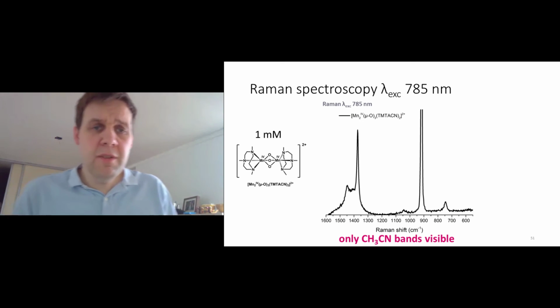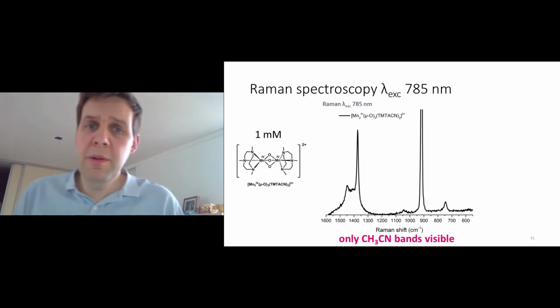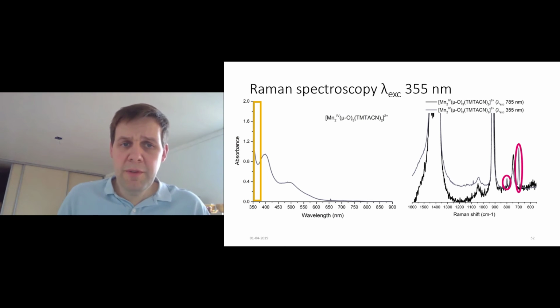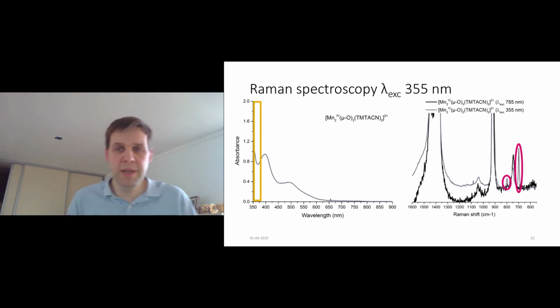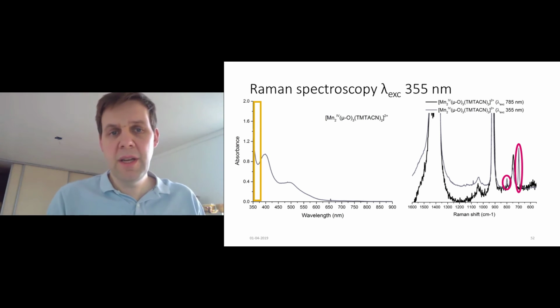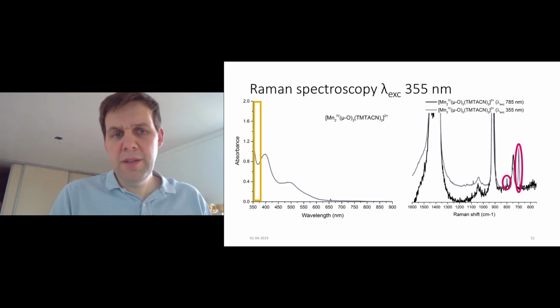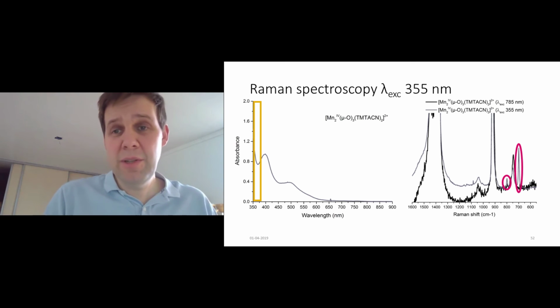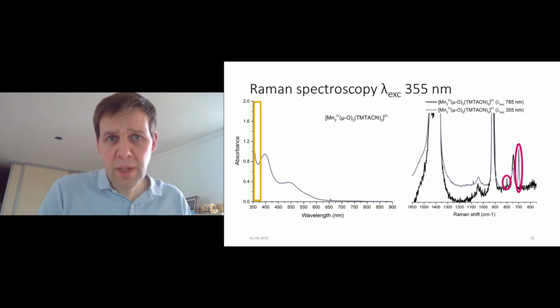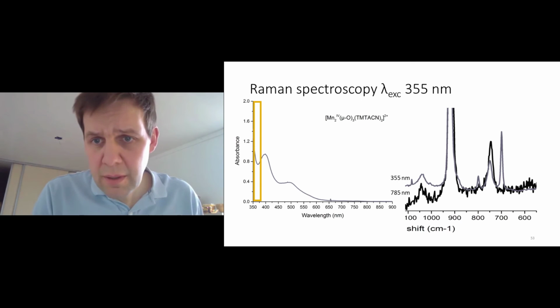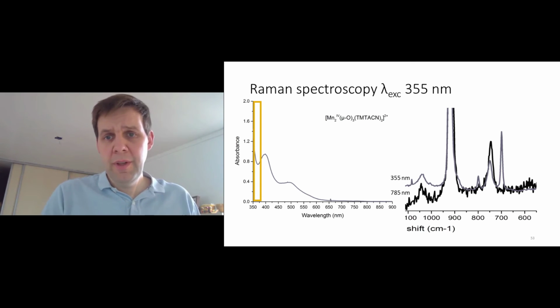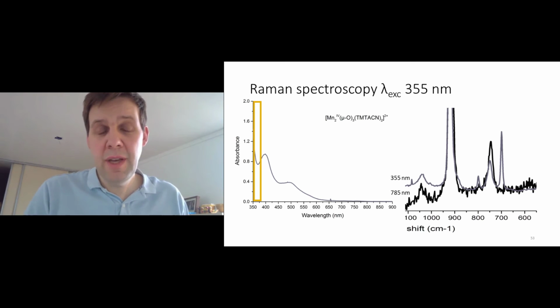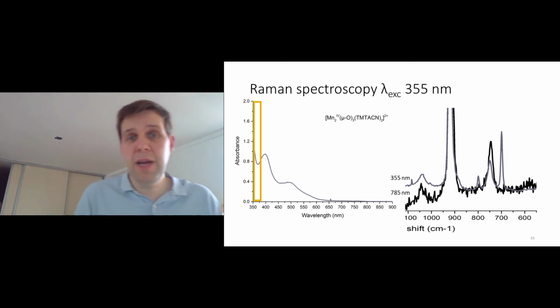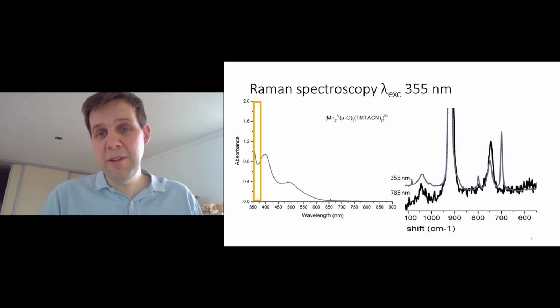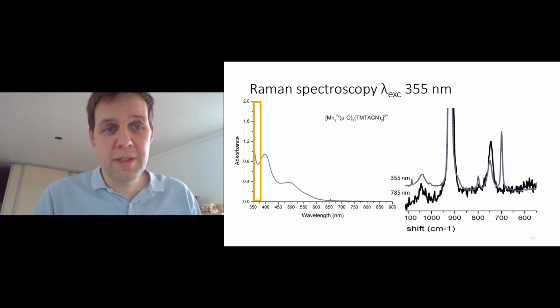If we take the complex of 785, 1 millimolar, it's too low a concentration to be observable by Raman spectroscopy. If, however, we move to 355, we hit into a metal to ligand charge transfer band, ligand to metal charge transfer band, so it's oxo to manganese. If we compare the spectra, we see the appearance of 2 new bands. All the rest of the bands aren't there, but 2 new bands appear at 355 that are not present in the same solution at 785, so these are resonantly enhanced. If we zoom in, you see more clearly. You also see the signal to noise is a bit better at 355 than at 785. That has nothing to do with Raman spectroscopy. That just happens to be how often you acquire and how much you average your signal and so on. So this is purely experimental settings, why there are differences in signal to noise.